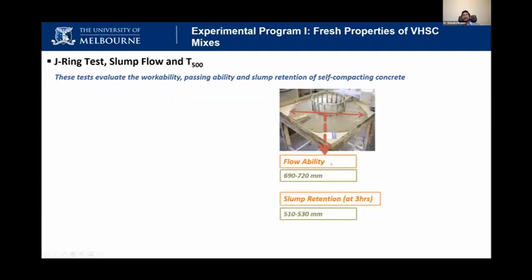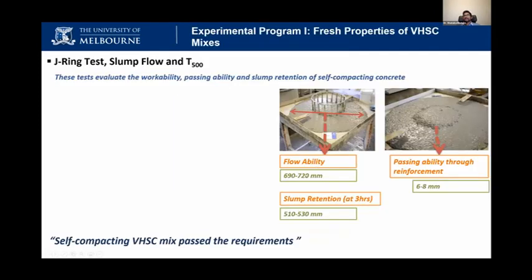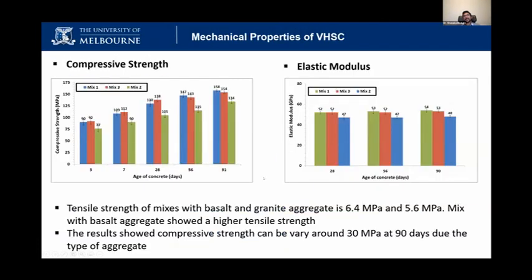So, right. The flowability, the spread, was around 720 millimeters, and the passing ability should be less than 10 millimeters, so it's satisfied. Slump retention at 3 hours was satisfactory. It should be around 500. So we were able to achieve not only the strength but also the workability requirement.